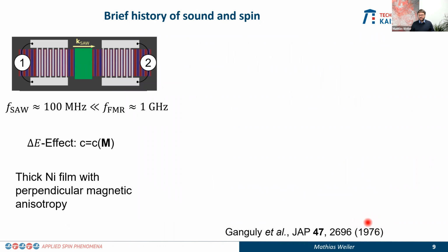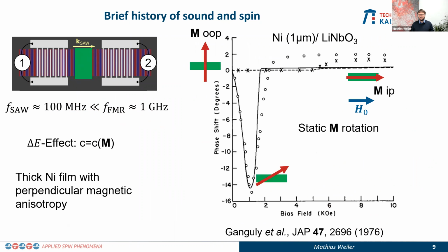Going a bit on in history, 1976, there was a follow-up experiment at rather low frequencies, 100 megahertz, far below the FMR frequency, in this case also a nickel film. There was this experiment over here where the authors showed that because of the static rotation of the magnetization, when one varies the external magnetic field, there was a field applied in plane, but a perpendicular magnetic anisotropy thin film of nickel. So you have a region where the magnetization points at some oblique angle to the out of plane direction, and that via the delta E effect causes a modification of the elastic constants of the nickel that depend on the orientation of the magnetization. So there was already shown an influence or a coupling between the surface acoustic wave and the magnetization, but this was, so to say, static.